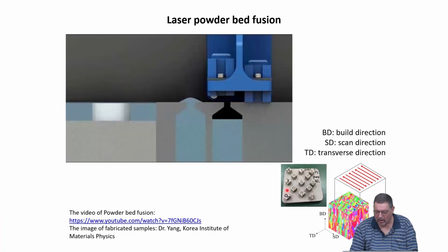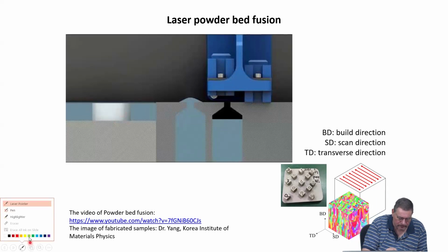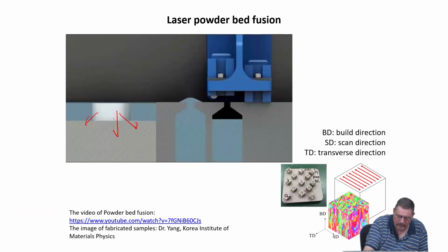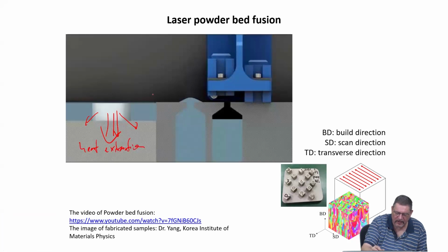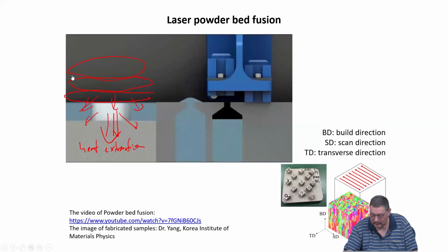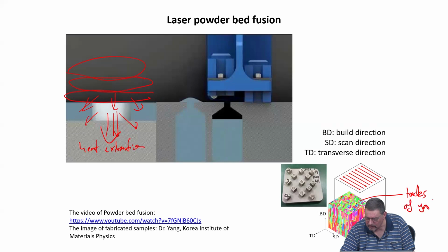The problem here is that you cannot avoid obtaining structures which have a very, very anisotropic microstructure, because the heat is extracted in this direction, a little bit in this direction, and a little bit in this direction, but mostly in this direction. And the next layer will again deposit heat, and the next layer, and the next layer. So it means you will always see the tracks of your deposition melting.